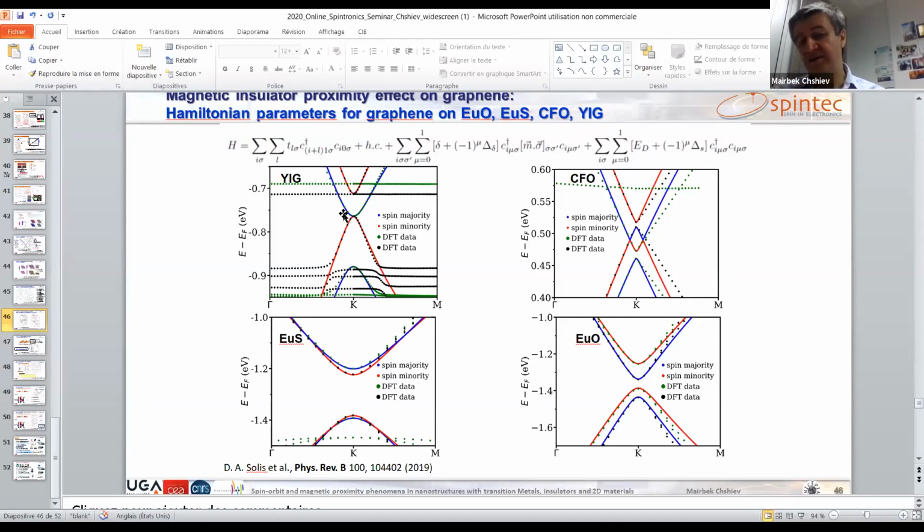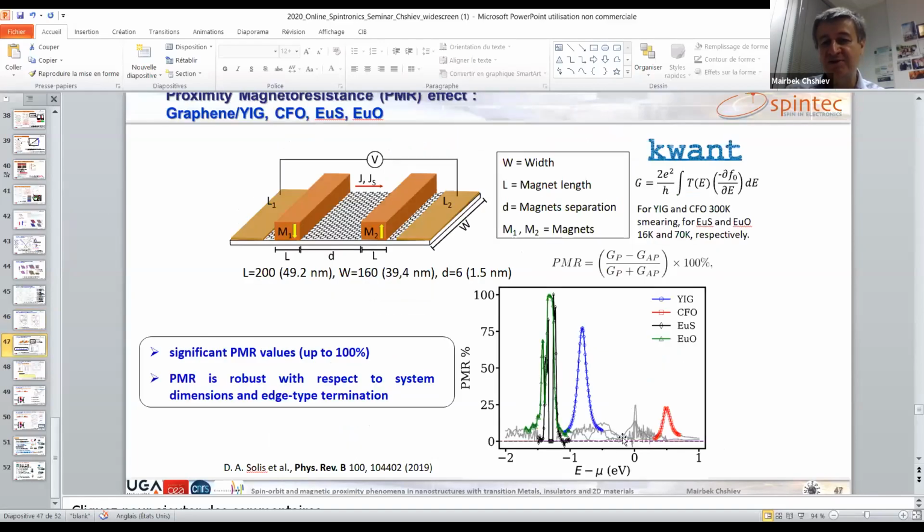But the idea is, yes, I don't know, Kirill, if I'm answering you, but be careful that here we are having electron doping, and all the large magnetoresistance you will expect only within this region where you have a heavy spin splitting. Obviously, if you look at what happens in the upper region, the situation is different, and therefore in that region you are not getting large magnetoresistances, you are having some noise. So you need basically to have the Dirac cone somehow tuned to the Fermi level. Correct. Yeah.